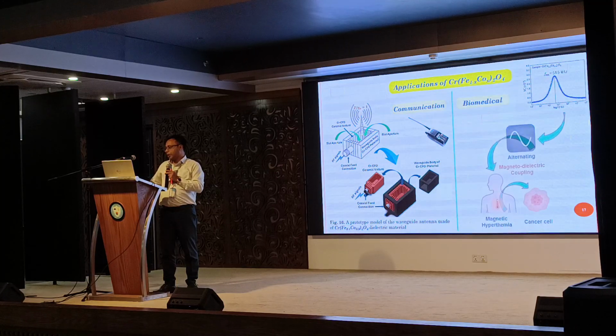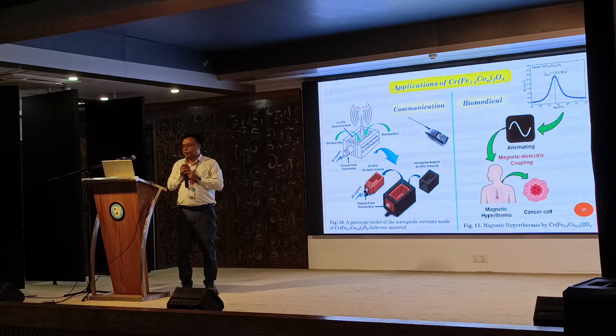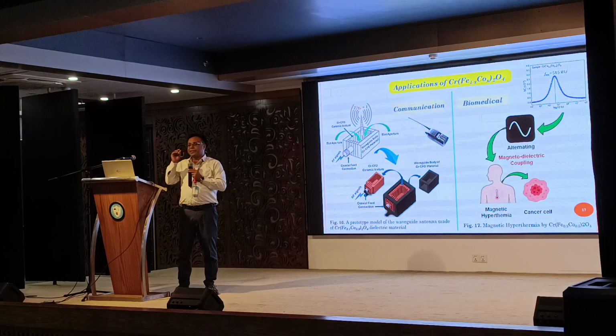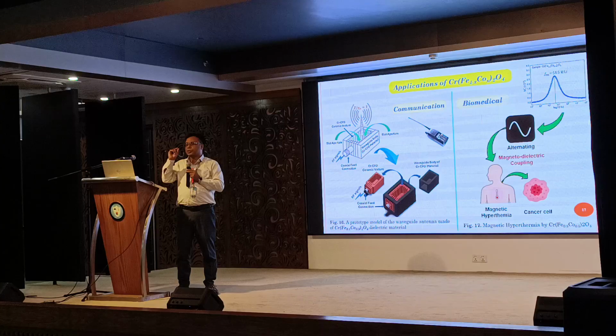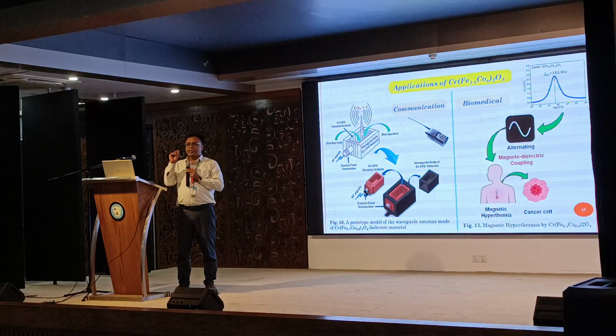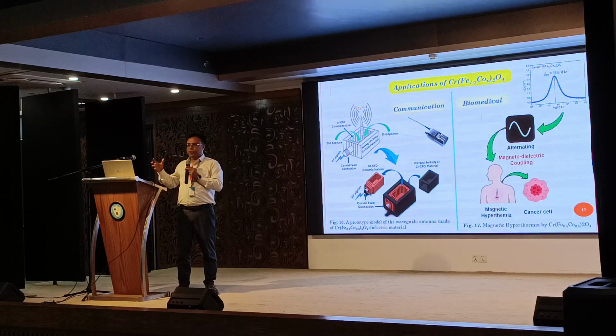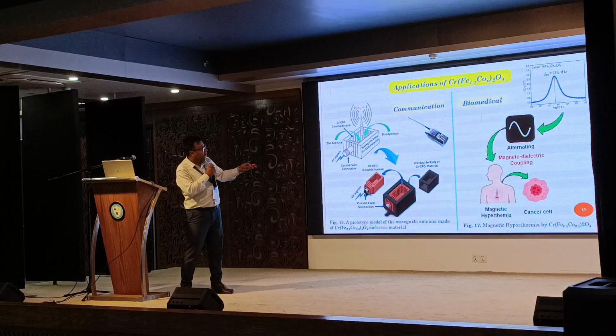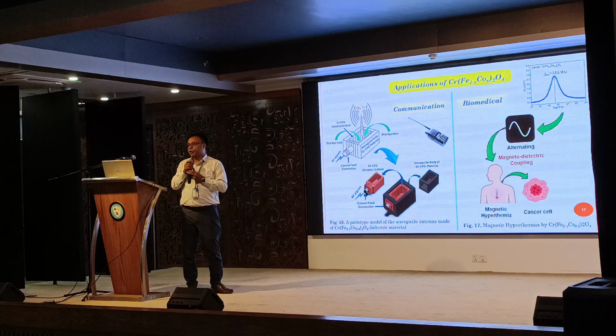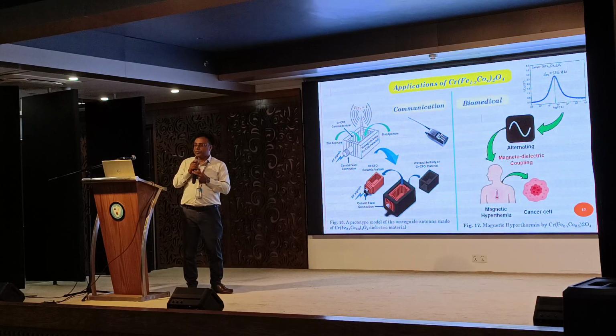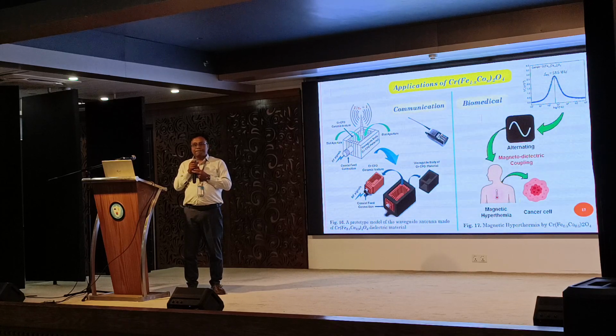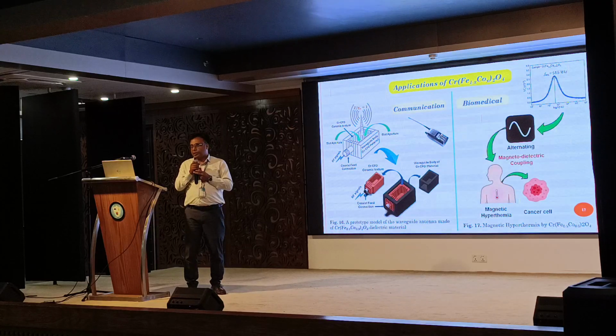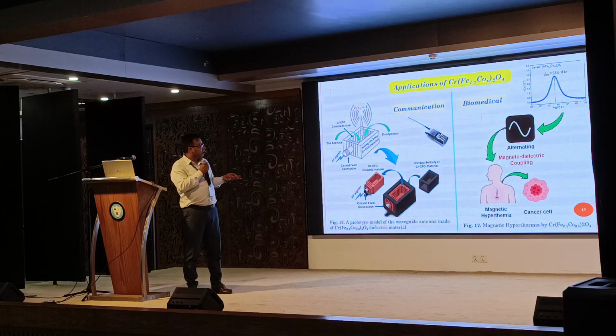Another one is a biomedical application. I told you that these materials will function by generating some heat to kill cancerous cells. A cancer cell needs 40 to 44 degrees Celsius temperature to be killed, and in an indirect way we calculated that if we apply this type of frequency, a 51.5 kilohertz AC magnetic field, it can successfully destroy the cell without causing harm inside the body. It can generate 40 to 44 degrees Celsius of temperature, and from this graph we confirm it. Now we need to implement it. We are waiting for the implementation.